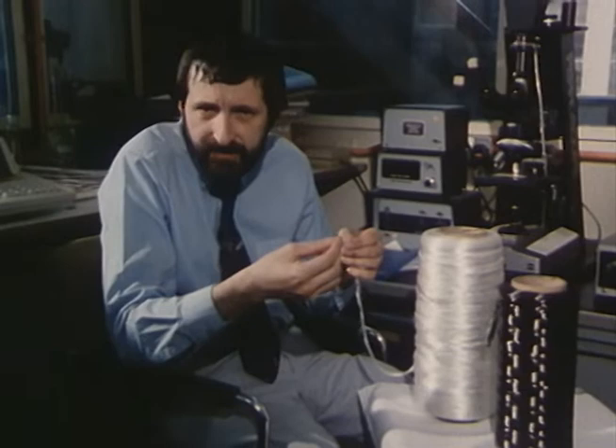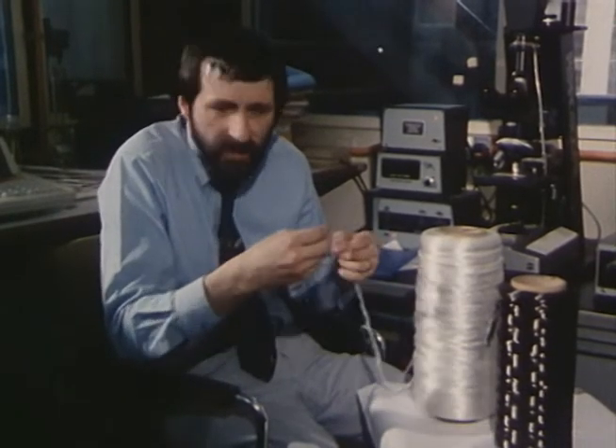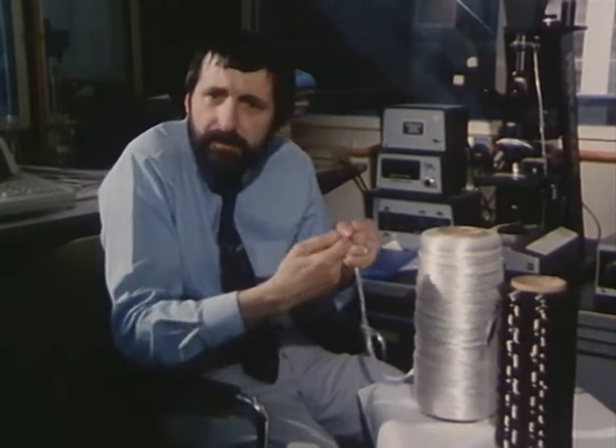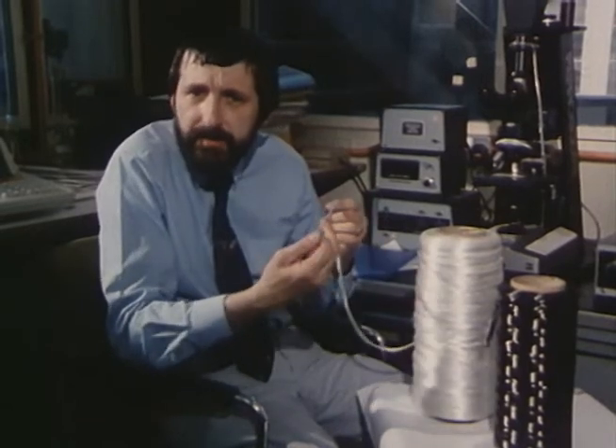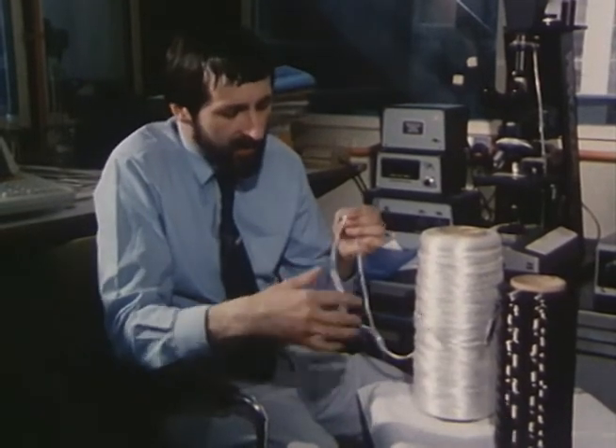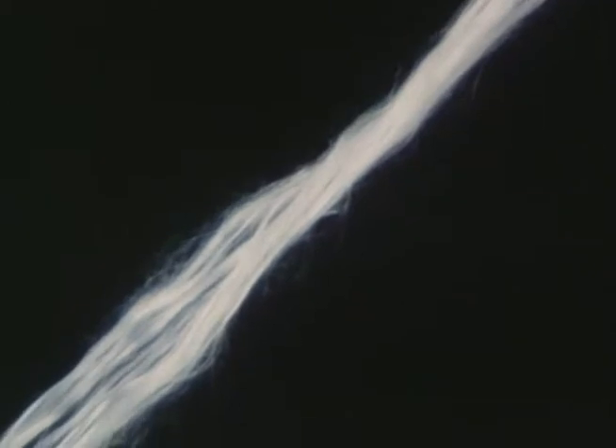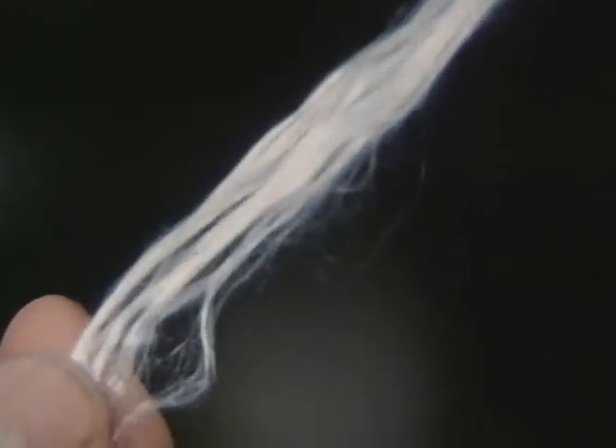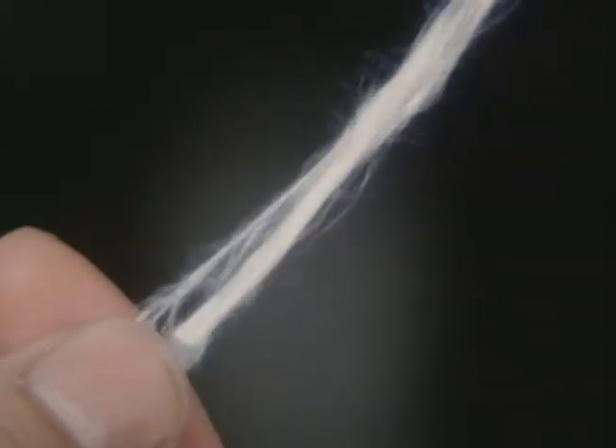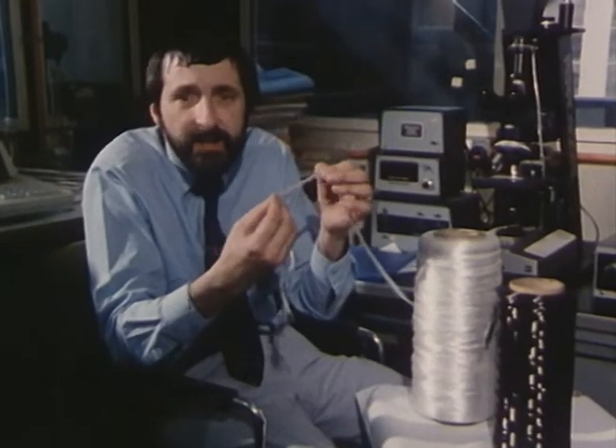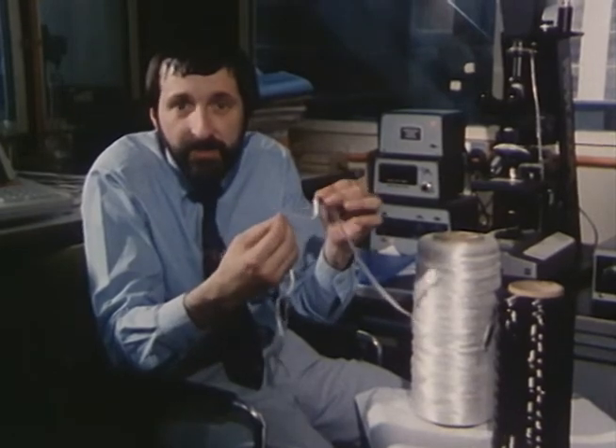A materials scientist, A.A. Griffith, had discovered a way of making materials almost as strong as the bond between the molecules themselves. He found that by pulling very fine fibres of glass, he could make a material that had no internal faults. And this material, as it stands, is 13.5 times stronger than mild steel.